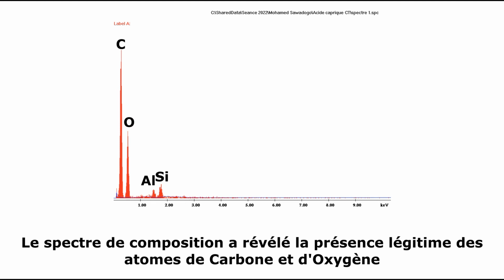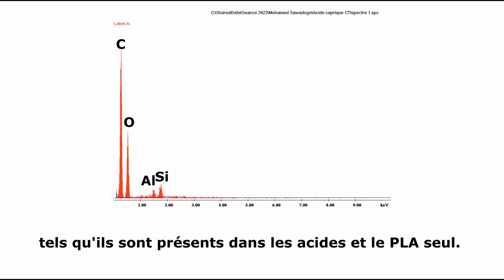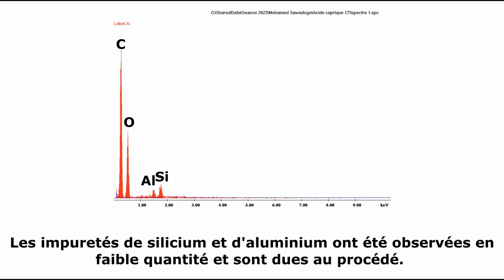The composition spectrum revealed the rightful presence of carbon and oxygen atoms as they are present in the acids and PLA alone. Silicon and aluminum impurities were observed in a small quantity and are due to the process.